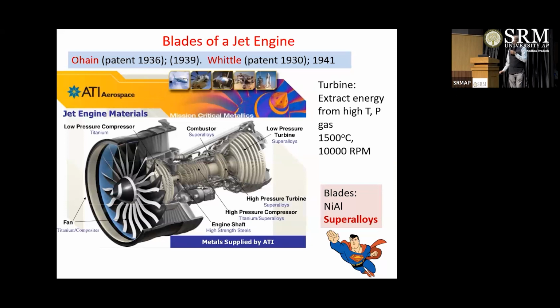Unfortunately, that means to fly from London to New York, you can only afford a certain amount of fuel on the plane because it's too heavy to carry. And you need a high efficiency engine which can use just that much fuel to fly that distance. So the temperatures at which this has to be operated is around 1500 degrees centigrade at 10,000 RPM. And for that, you need a material which will still be strong and not break down.